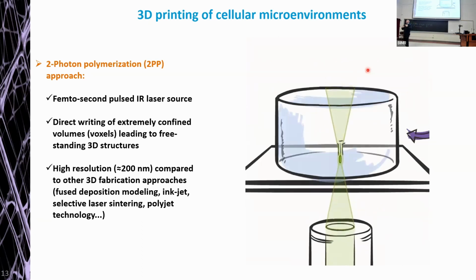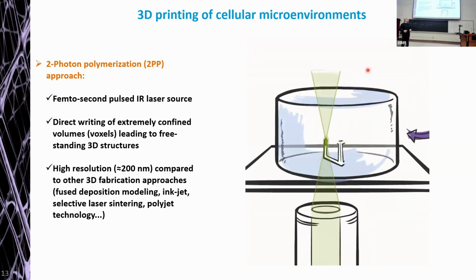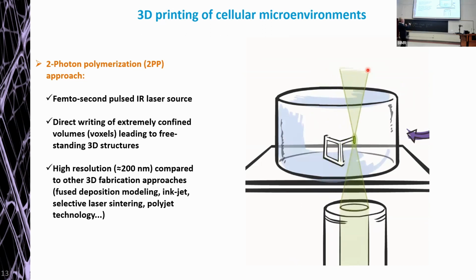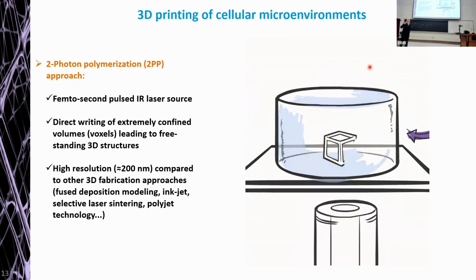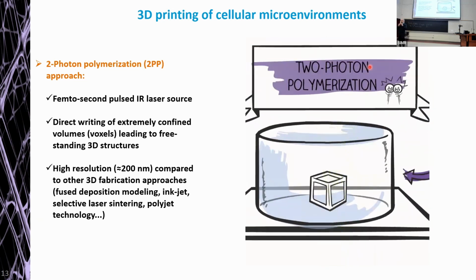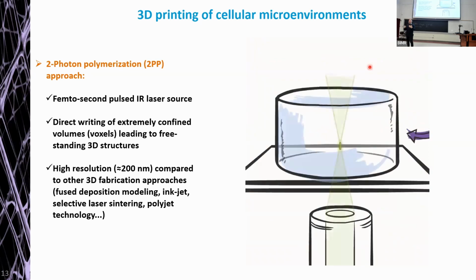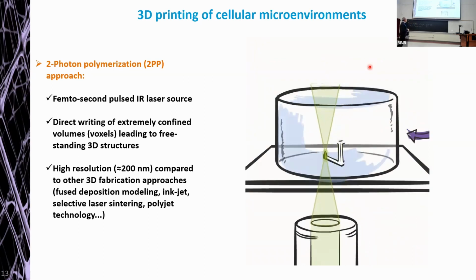By exploiting a phenomenon which is called two-photon absorption, by means of which two infrared extremely fast photons are absorbed almost simultaneously by the material in a very confined volume, it is possible to create 3D freestanding structures without the need of sacrificial support, because in this case, it is the non-exposed material that supports the structure, with a feature resolution that can go down to 200 nanometers, which makes the 2PP the technique with the highest feature resolution achievable.